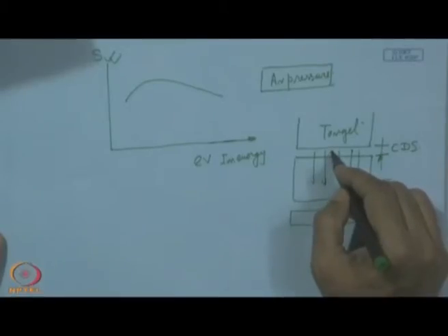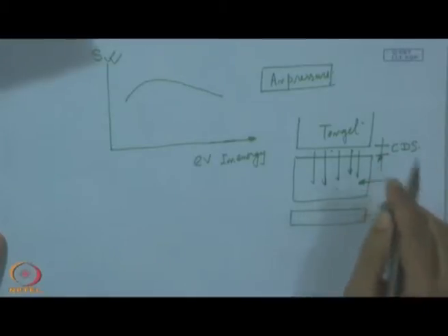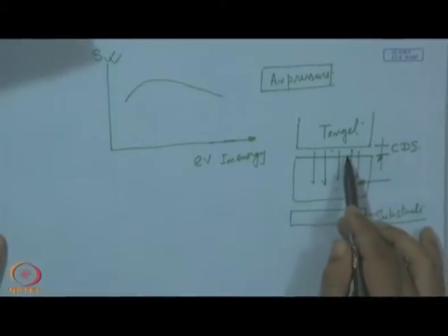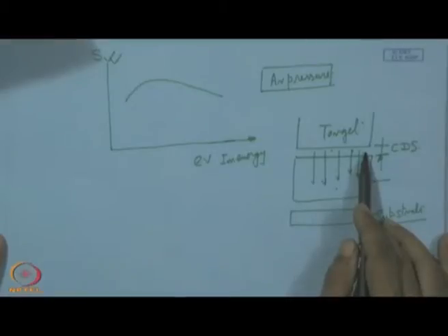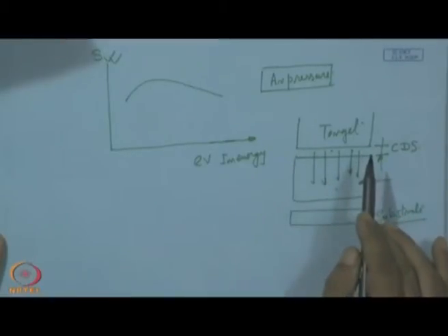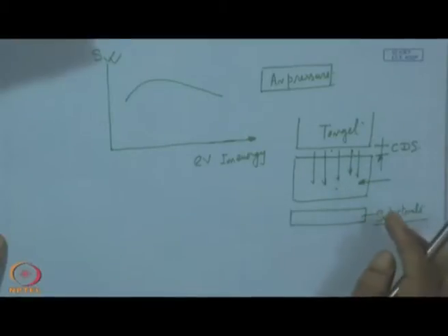So, the whole thing is that this secondary electron enters this plasma volume and that becomes the primary electron, and then they are going to strike. So, what we see from this whole process is that these secondary electrons are not efficiently used in the close proximity of the target, where we need the concentration of ions and high energy ions in this vicinity of this target surface. So, that is the whole issue.